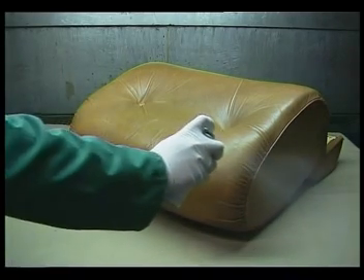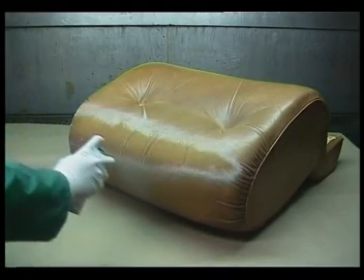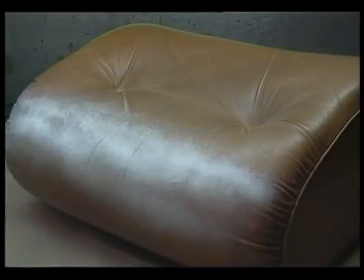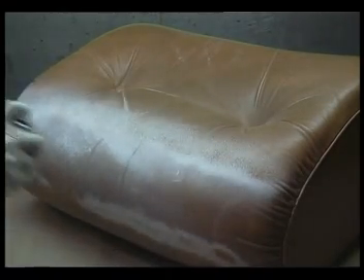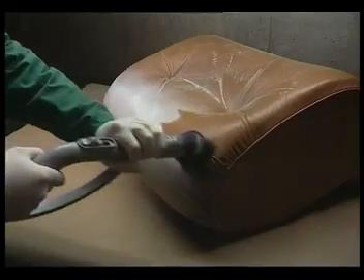Simply spray a heavy coat of leather degreaser on any greasy part. It will dry to a white powder that will absorb grease from the leather. Leave the powder to work for at least 4 hours, preferably overnight. Do not dry with a hairdryer, as it will prevent the product's degreasing action. Remove the powder from the leather using a vacuum cleaner with a soft tip, and then clean the leather with leather cleaner.